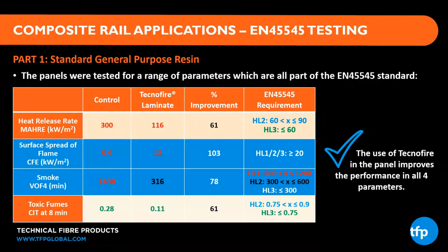If we look at the improvement of incorporating the 0.5 millimeter layer of Tecnofire, we've got a 78% improvement. We've dropped that smoke generation down to 316. And if you look at the requirement for HL3, the highest level of performance, that's a maximum of 300. So we're right on the borderline of having an HL3 smoke performance here, going from a system that was failing HL1. And if we look at the toxic fume, the CIT, the control has a toxic fume at critical index of toxicity of 0.28. That's been improved by 61% to 0.11. The HL3 requirement is less than 0.75.